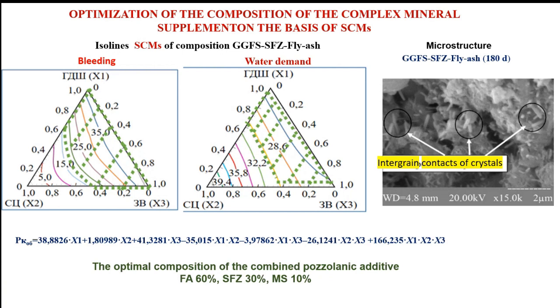The optimal composition of complex pozzolanic materials blends is determined by the strength activity index. The combined effect of components on the pozzolanic activity after 28 and 90 days was investigated using the Scheffé simplex lattice plan method. For the three-component mixture, each point of the triangular diagram corresponds to one ratio. The regression equation is presented as follows. The optimal composition of the combined pozzolanic additive is fly ash 60%, superfine zeolite 30%, and microsilica 10%.